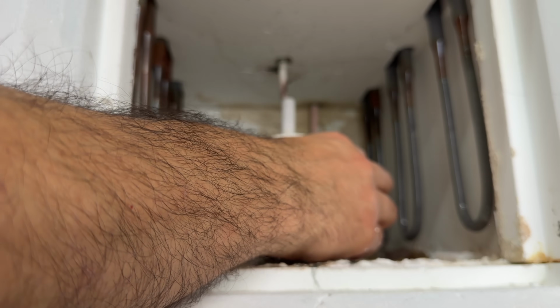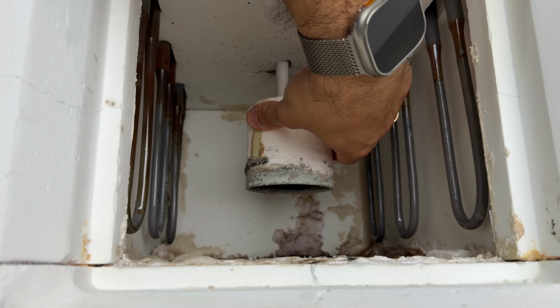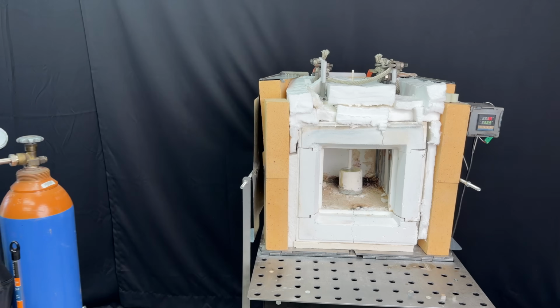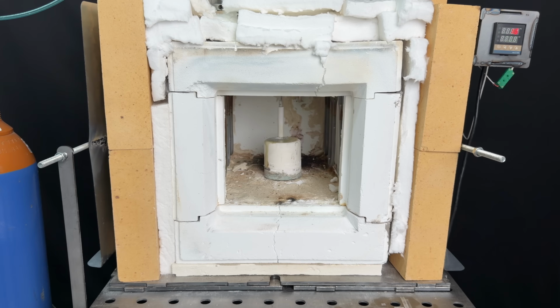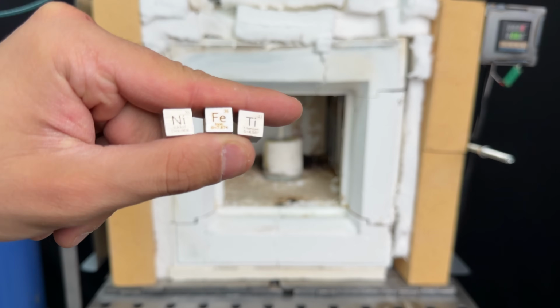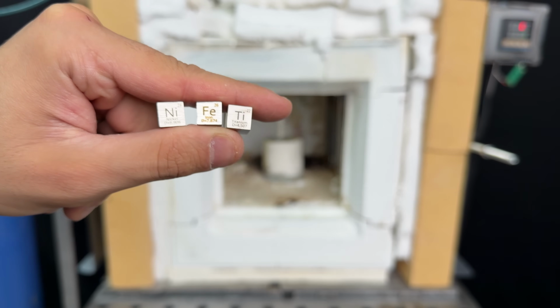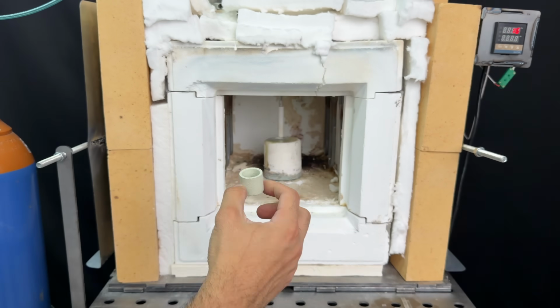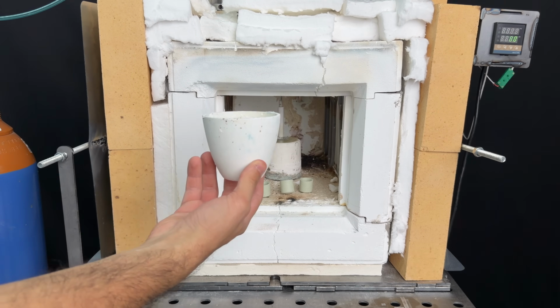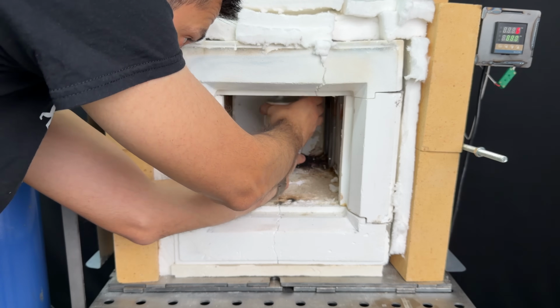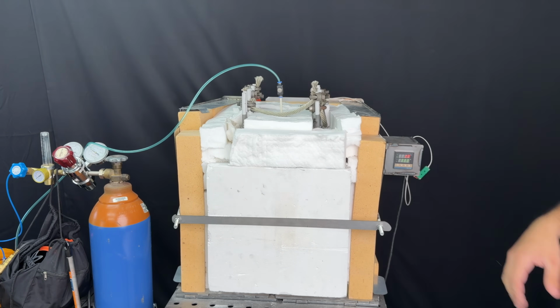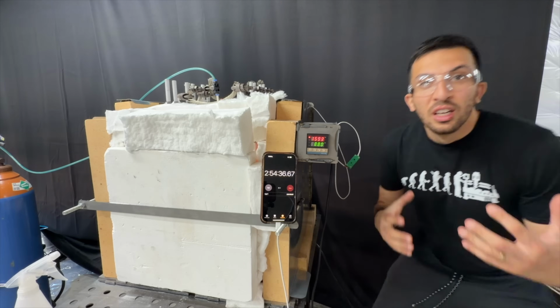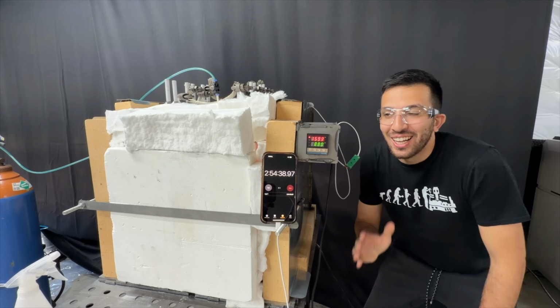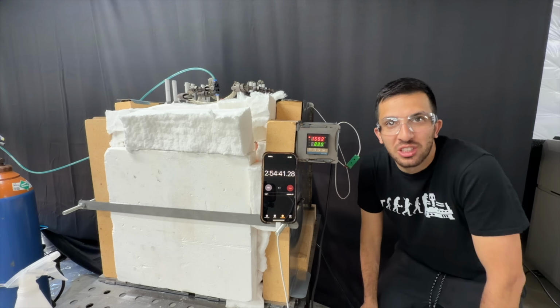First, we add argon gas to prevent oxidation, which interfered with our melting. We do this by piping gas through a ceramic tube into a dome, and I'm using argon from my welder setup. Next, we use much larger chunks of the metals, which are also labeled nicely. I'll put them in these small crucibles and place them in a larger alumina crucible, which will be covered by the argon dome. Lastly, we throw additional insulation where we witness the cracks in the furnace and we ramp it all back up. So our heating has tapered significantly here, again at around 1600 degrees Celsius.